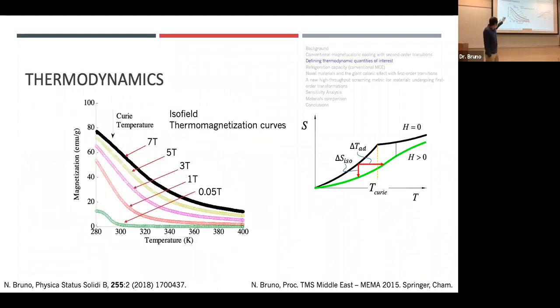So here is the magnetization versus temperature response of a typical ferromagnetic material. Sort of ignore the lower green curve here. But if we were to use this material as a solid state refrigerant, we would first reach about room temperature, which is 300 Kelvin. And we'd just cycle the magnetic field really quickly and measure what temperature change we get.